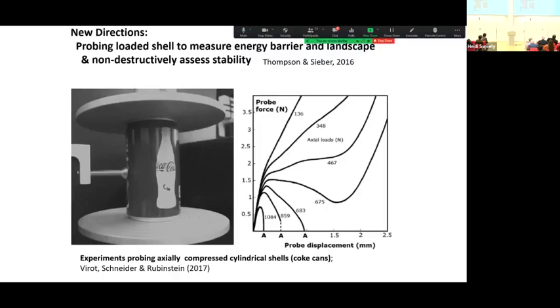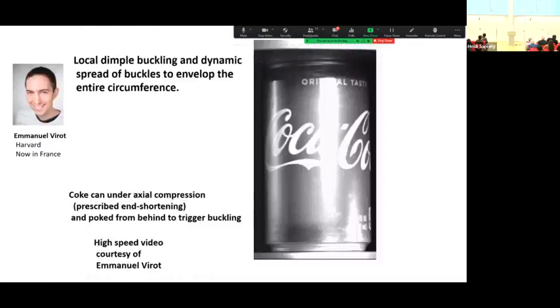It's probed, and you can see when you probe it, this is the probing curve. So the probe force increases, then it starts to give a bit. You're still probing. You've got to stop at A, otherwise it'll snap. But at A, it'll snap. And so you can cross plot these and extrapolate to the point where it'll buckle. And it buckles at, I think, about 1,100 newtons.